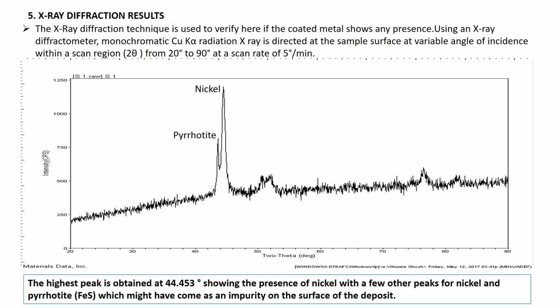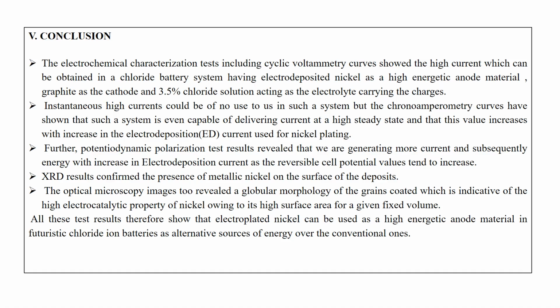the deposit. So the conclusions: the electrochemical characterization tests like cyclic voltammetry show that high current can be obtained in the chloride battery system having electrodeposited nickel as the high energetic anode material. The potentiodynamic polarization tests reveal that we are generating more and more current and subsequently energy with increase in the electrodeposition current.